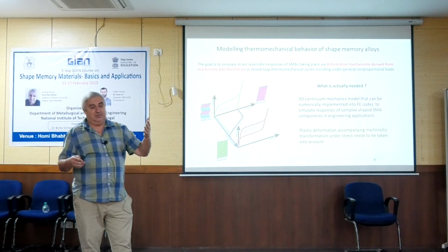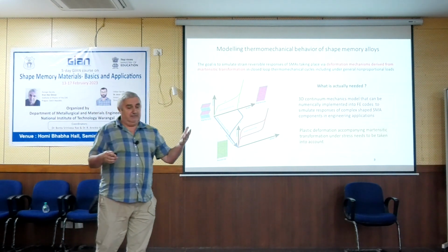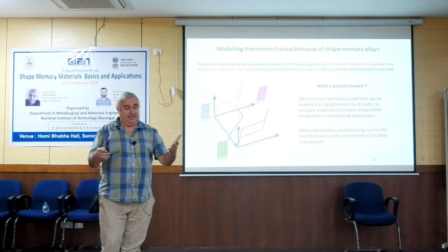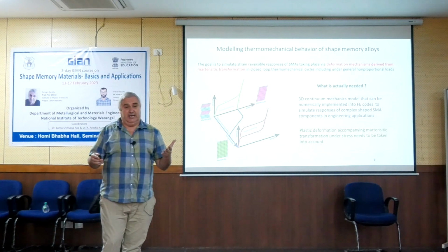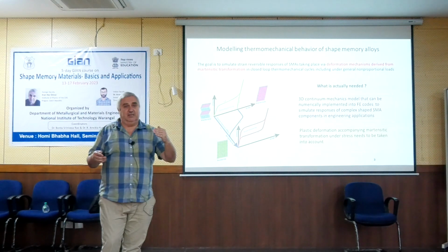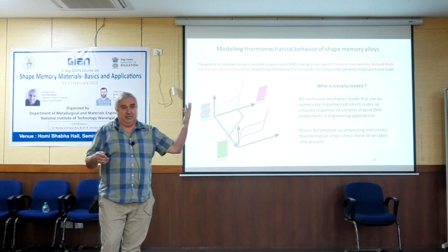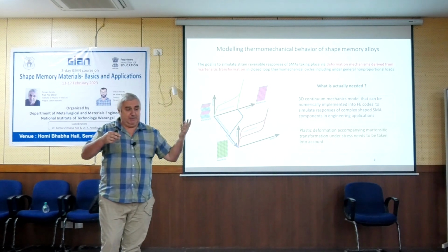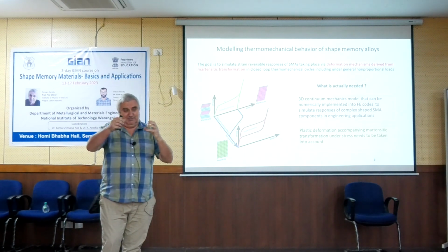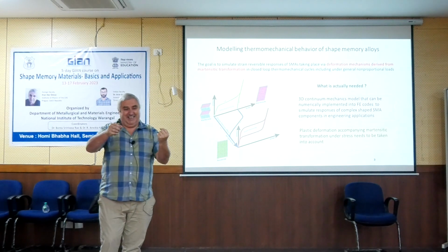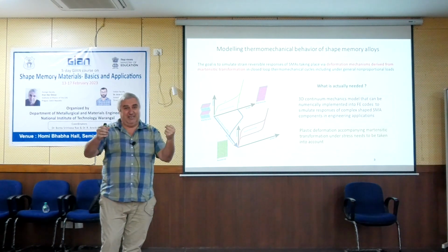One is just to include plasticity, like in a plastic deformation model. The other is to include TRIP, transformation-induced plasticity, which is plasticity which proceeds alongside the transformation. But this is in steels. TRIP steels are very famous. In TRIP steels, you have transformation and plasticity going side by side, but in different places.